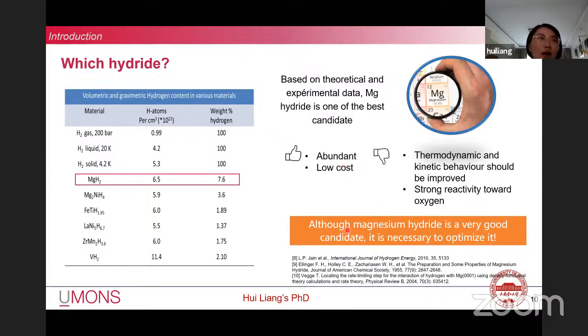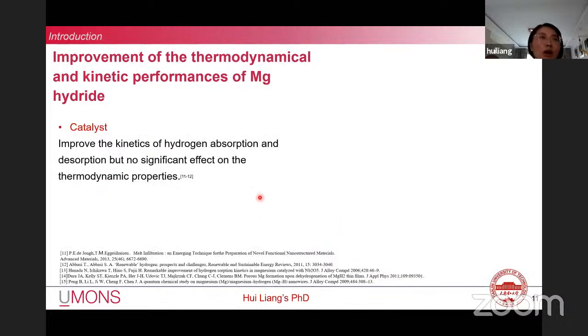But for MgH2, its thermodynamic and kinetic behavior should be improved, and Mg can easily be oxidized. This would lead to poor cycle performance. Facing the problem of thermodynamic and kinetic performance, the commonly used solutions use a catalyst and preparing nanosized material. However, the catalyst could only improve the kinetic property, but has no obvious effect on the thermodynamic properties, and also